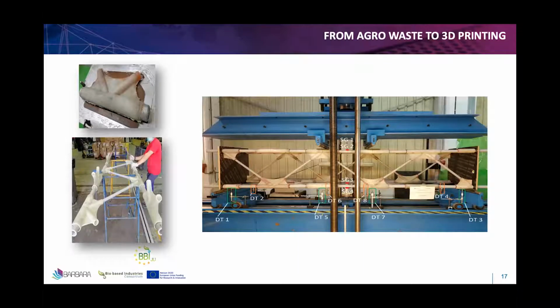So with all the joints that we were able to produce with the mold, these were configured in the truss that you can see in the images, and they were tested under 35, 50, and 75 kilonewtons, applying the load 3 times, and no damages were observed. Thus, there was structural integrity of the truss, and the piece produced with our mold was of very good quality indeed.